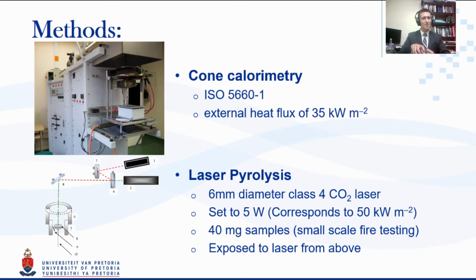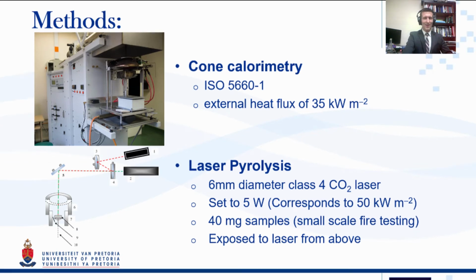So this is a micro scale test, and we set the laser that we expose it to have a 5-watt power setting, which corresponds to 50 kilowatt per meter squared, which is a very, very well developed large scale flame. So we really put it to the test. And I'll get to the results on that a bit later.